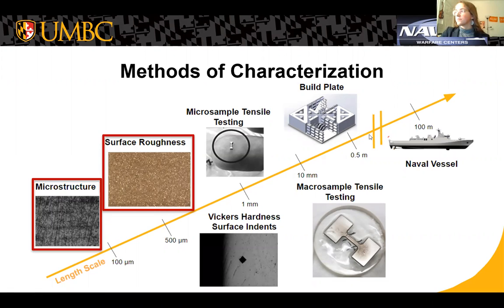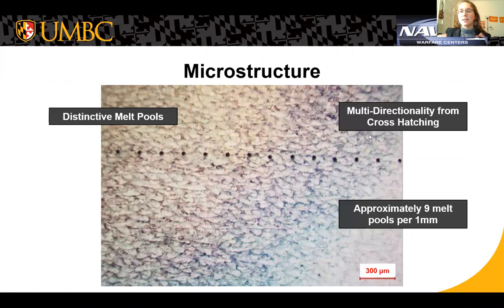So here you can see the microstructure that we were able to get from one of our thin fin surfaces. And you can tell it has very distinctive melt pools that point in different directions, and that's, as I previously mentioned, the cross-hatching. As each layer is fused in a different direction, it forms these crisscrossing patterns. And it's approximately 9 melt pools per 1 millimeter.